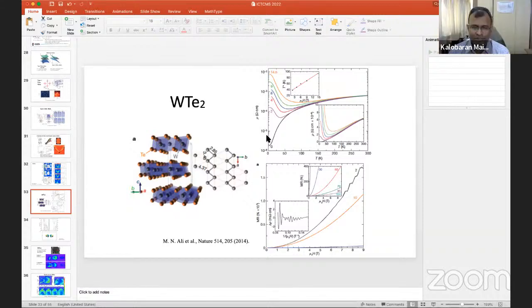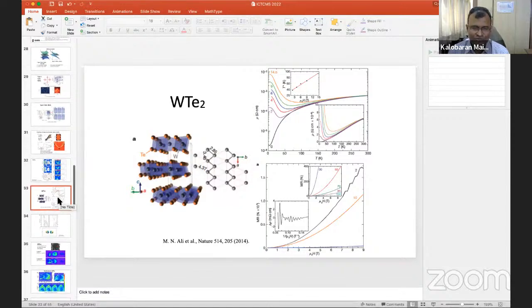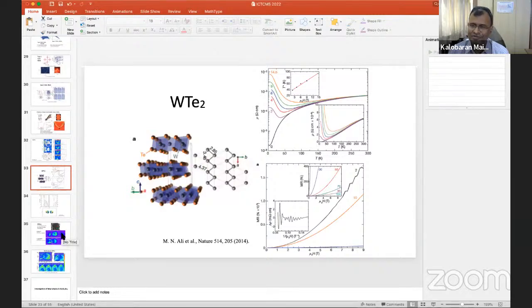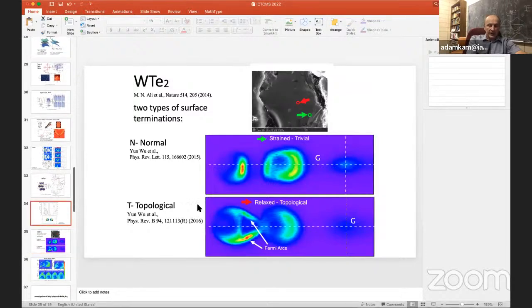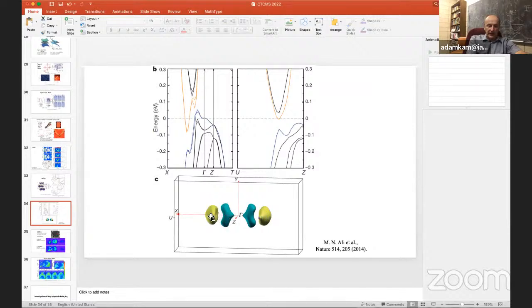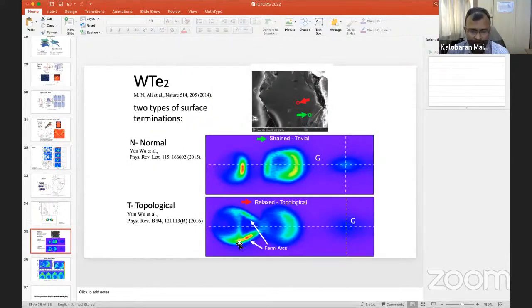Okay. The other point which I wanted to know from the experimental point of view is, from ARPES, do you find any signature to identify these Weyl nodes and Dirac nodes? Right. So the only evidence we have for tungsten telluride is the presence of Fermi arcs. If you look at the calculation of the Fermi surface here, there are just disconnected hole pockets here and electron pockets here and hole pockets here. There's nothing connecting. The surface state calculation does not reveal anything. The only explanation for those features here is that these are Fermi arcs, and Fermi arcs in a Weyl metal mean there have to be Weyl points here. I see. So once you see the Fermi arcs, of course, that's a good signature. Right. Okay, thank you.